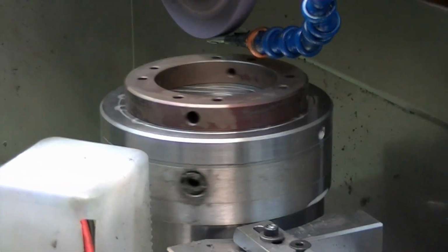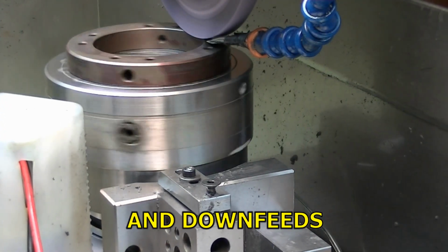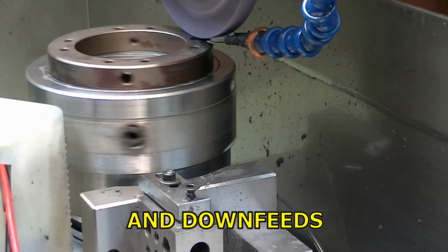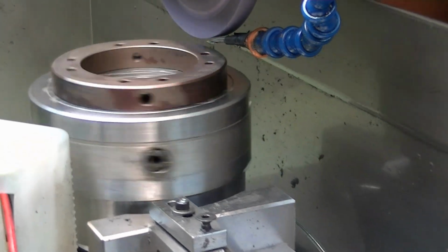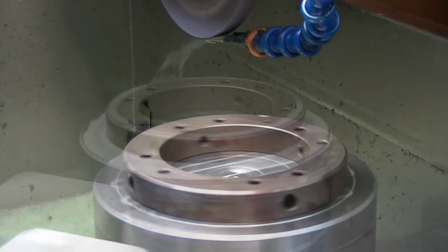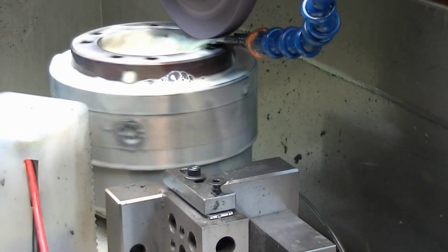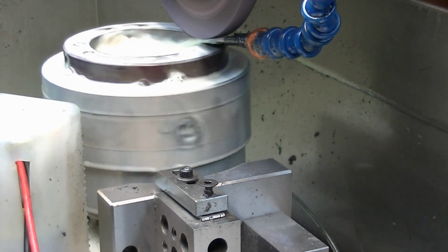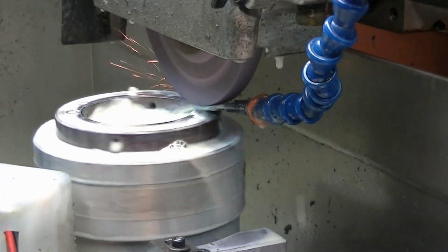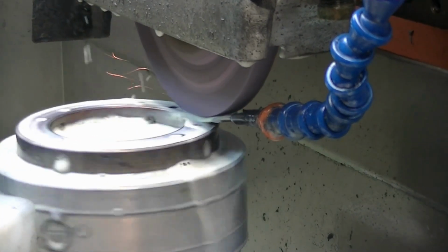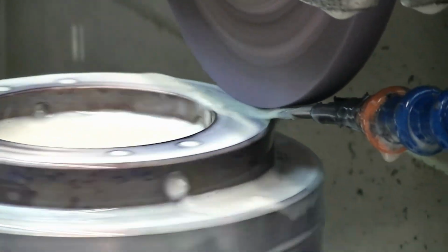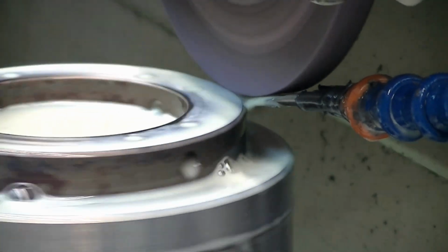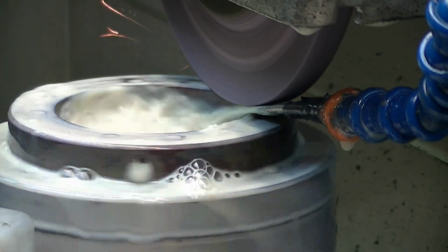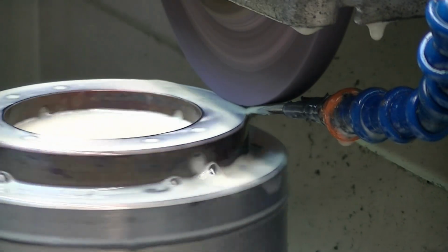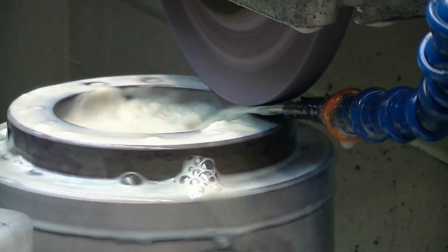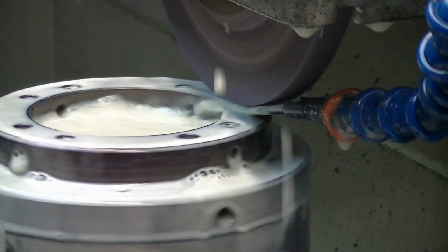Gets in the correct Z minus position, runs up to the center of the chuck in X, traverses across at whatever feed rate I have set, so it gets to the Z plus position and retracts. Here's the first grind pass. It's taking off enough to make sure where we are. It's just traversing across at a fixed feed rate that's set on the control panel. Wraps off. Now down feed again, and this is at 8x speed, and we're taking 2 more cuts to clean up.